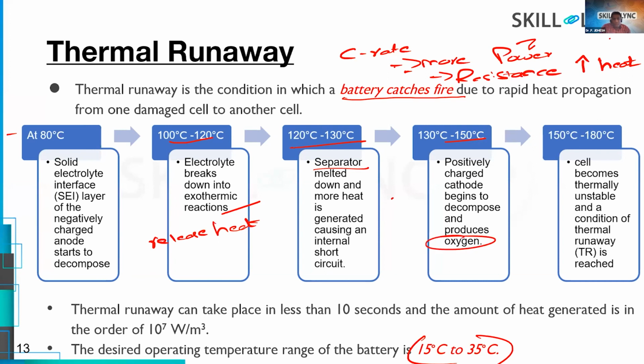After that, at 150 degrees Celsius, the positively charged cathode begins to decompose and produces oxygen. So we have gases, we have oxygen, which is enough to produce fire, right? The cathode layer produces oxygen, and during the exothermic reaction it releases more gases. When the temperature reaches 180 degrees Celsius, thermal runaway starts. The cell becomes thermally unstable and the condition of thermal runaway is reached. So the battery catches fire at 180 degrees Celsius.